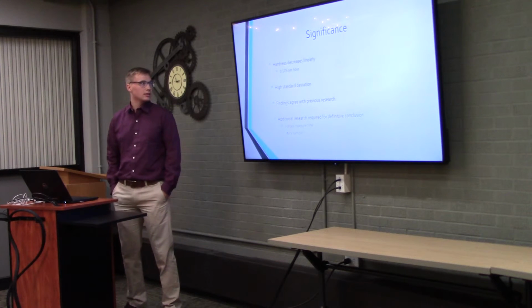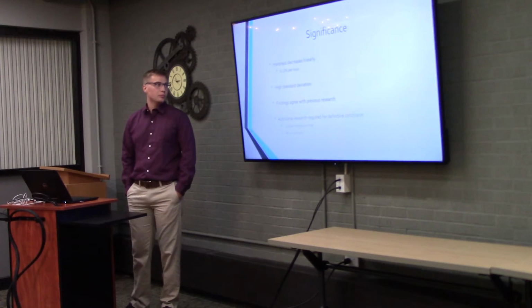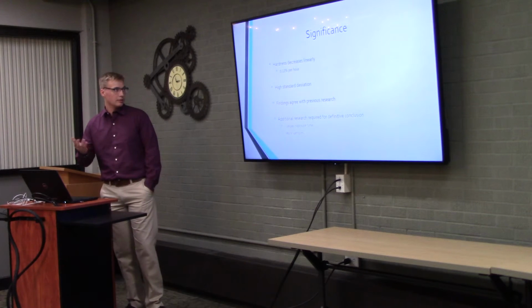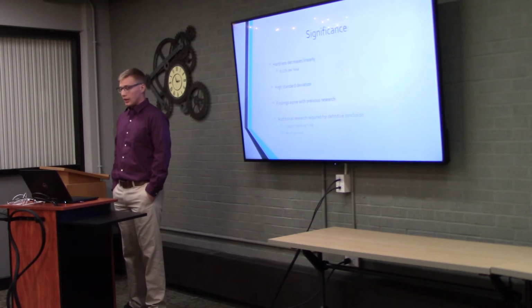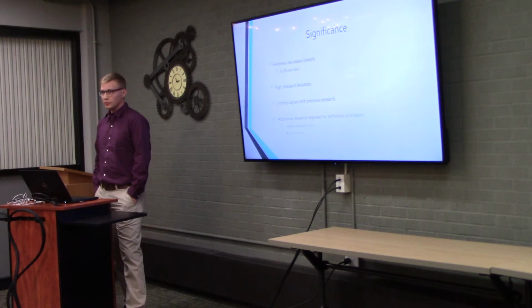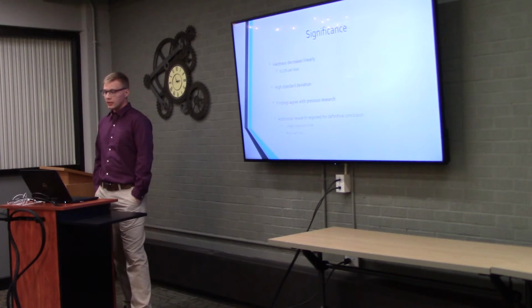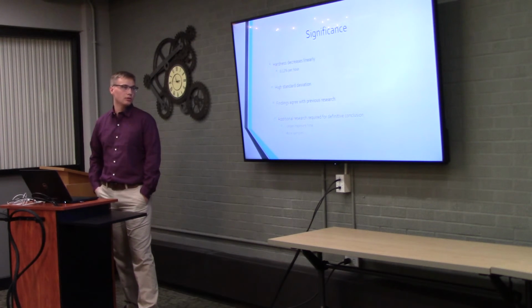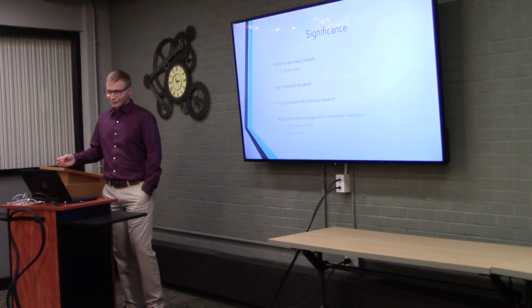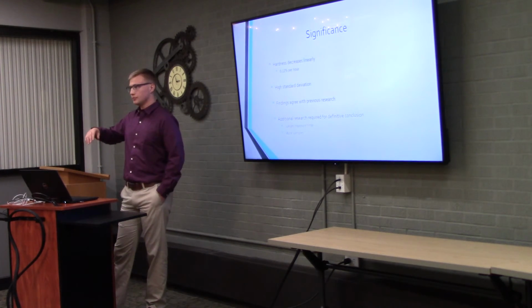So the significance of my study is the hardness was shown to decrease linearly at a rate of about 0.12% per hour, and this is a statistically significant linear relationship. And my study also showed a high standard deviation in the average hardness values, which, like I said before, could likely be down to hardness values being taken at the weakening grain boundaries. My findings also were found to agree with previous research, which did find noticeable corrosion after around the amount of time that I had in the Hastelloy N.